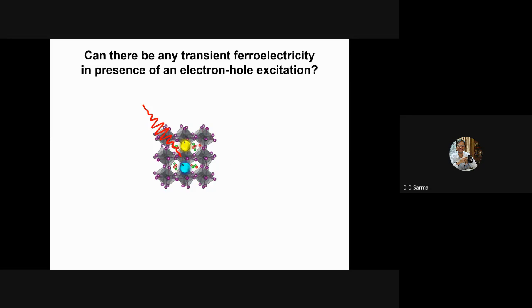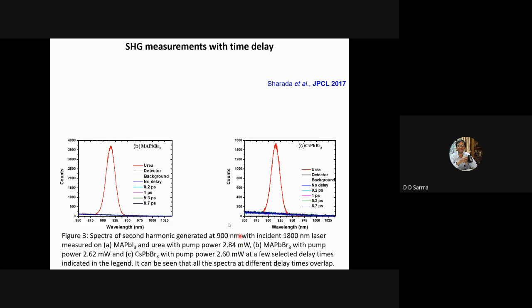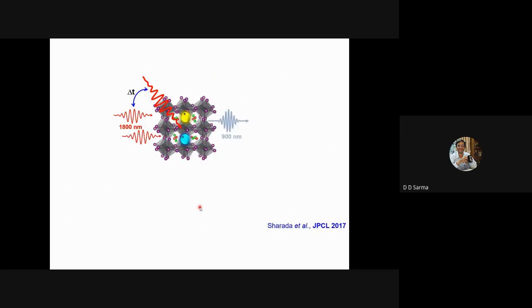We even checked this. The way we did that is after this absorption, we give a time delay and come in with a long wavelength and see if that wavelength is getting converted into half the wavelength or not, telling me after how much time, and I can vary this time. So I can start with something like 80 femtosecond after the absorption to all the way 1 nanosecond, 3 nanosecond after, and we have looked at the entire time scale from femtosecond to nanosecond, and we find no second harmonic generation, saying that in this excited state also, there is absolutely no polarity that is developing. I'll not tell you about this because I've told you the results already.